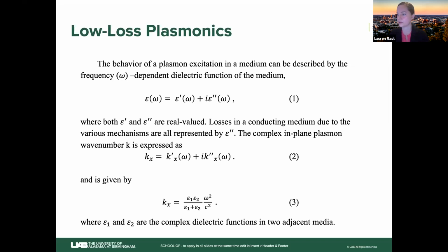So traditional metallic nanoparticles, like silver and gold nanoparticles of various shapes and sizes, are still in the pipeline for their full potential for industrial type applications. The main hindrance towards a more broad application of these materials are these losses that I mentioned before. In metals, primary plasmon loss mechanisms include scattering, radiative losses, and ohmic losses. And a different loss mechanism will dominate depending on the frequency, nanomaterial size, morphology, and the makeup of these nanoparticle systems. Radiative damping is smaller for these small particles, but even in the small size regime, ohmic losses of energy are still an issue.